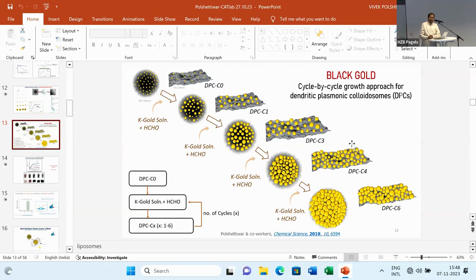Any comments? Now we haven't tried the graphene. I think any substrate which allows you to tune the gaps between the particles should work, right? Because the substrate itself is not really participating in the reaction. It's always the plasmonic coupling for giving the broadband light absorption. So ideally, any substrate should work. You can tune these gaps between them.